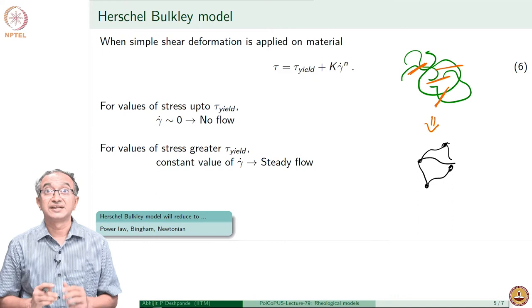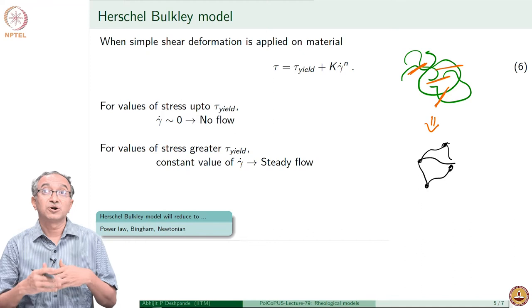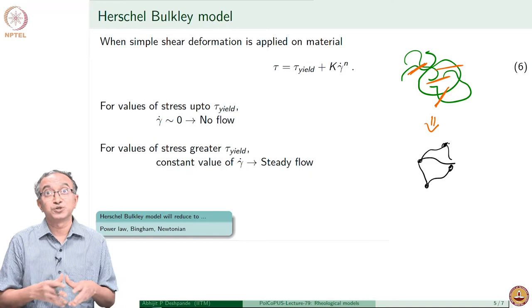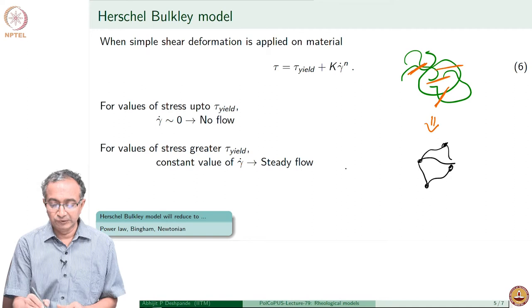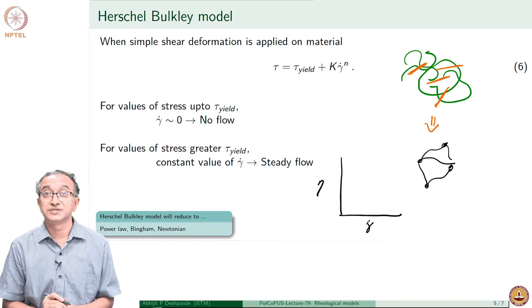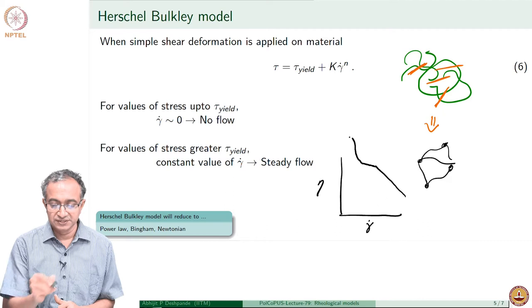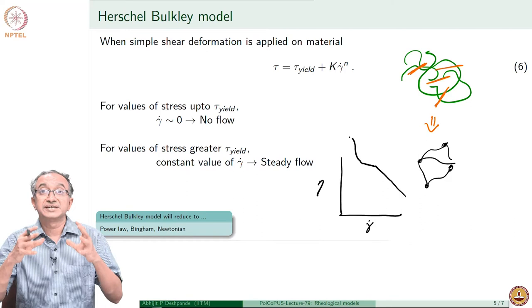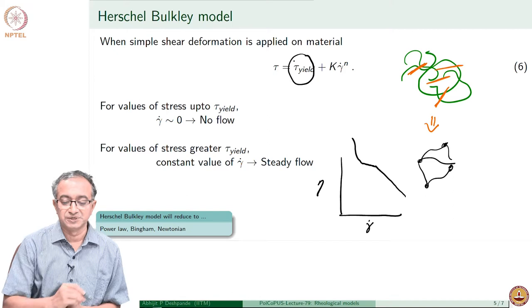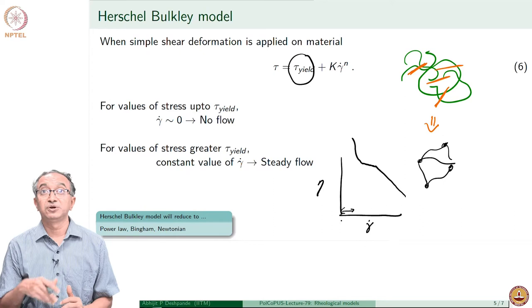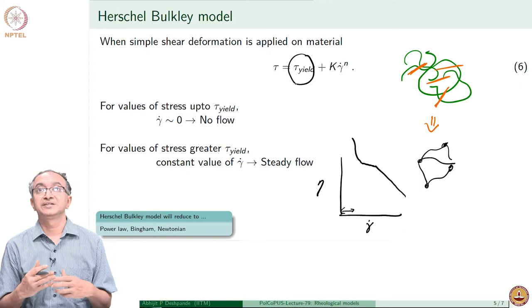When the network points are strong, the system does not exhibit viscous, fluid-like behavior but instead behaves more solid-like, similar to a cross-linked rubber system. Looking at viscosity as a function of strain rate for these systems, shear thinning is observed at higher strain rates, but at lower strain rates viscosity becomes very high because the cross-linked points make the material respond almost like a solid — resulting in a yield stress. Generally up to a certain strain rate there is no flow, and beyond that, once stress has exceeded the yield stress, flow starts and these materials are called yield stress fluids.